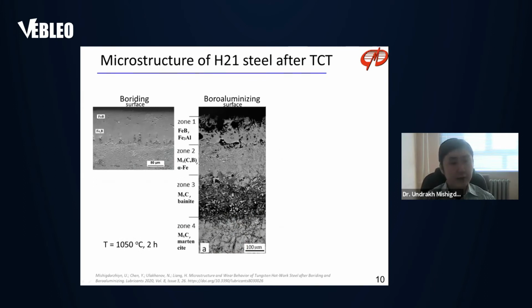After boriding, a two-phase layer was obtained with a tooth-like microstructure and a thickness of just above 100 micrometers. After boroaluminizing, a complex microstructure was obtained with a thickness of around 560 micrometers. Several specific zones can be distinguished in this microstructure.